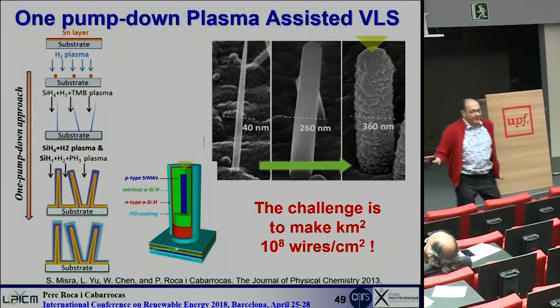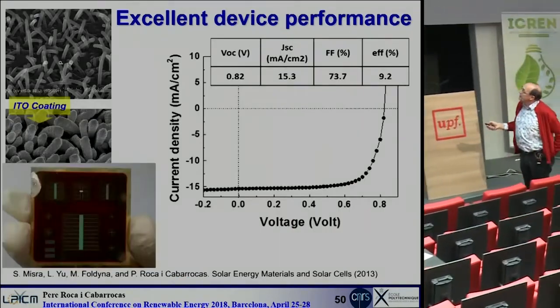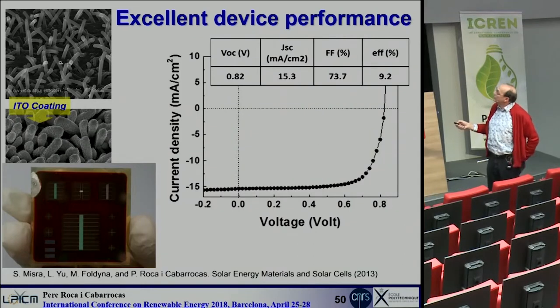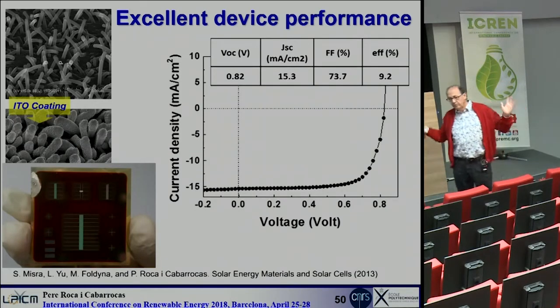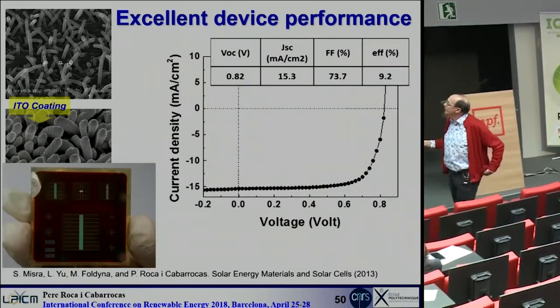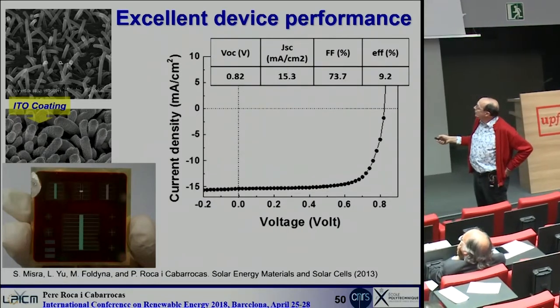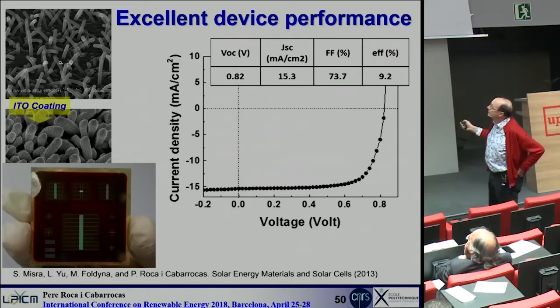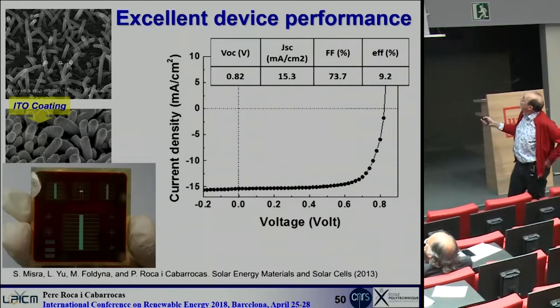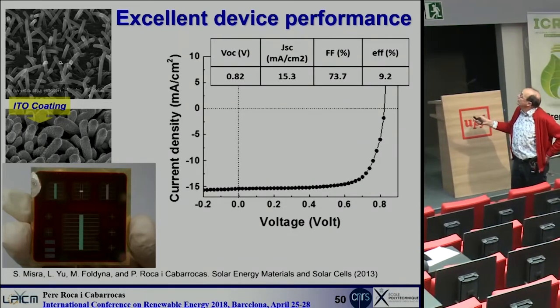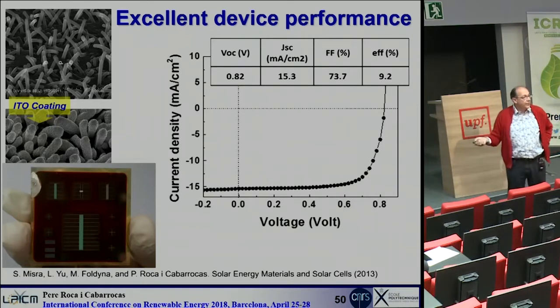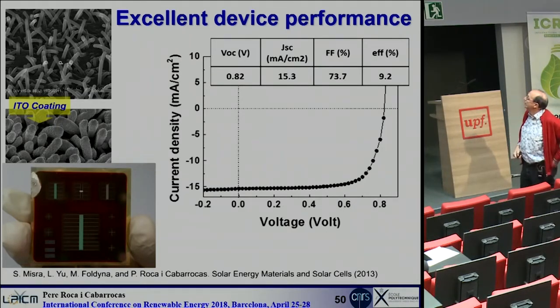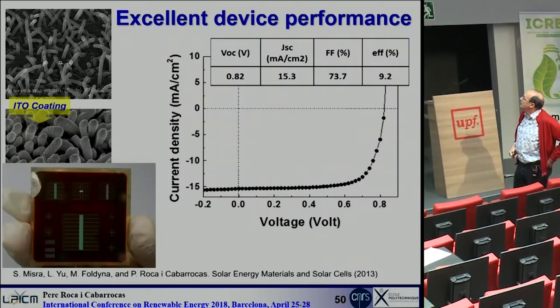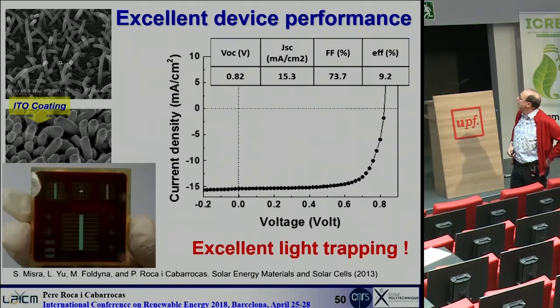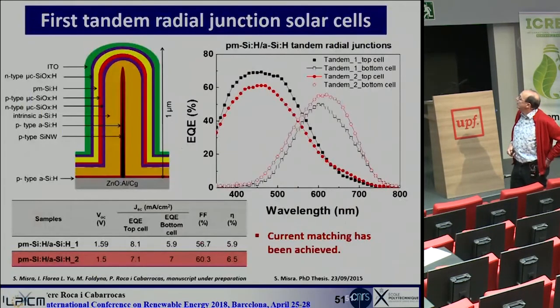Don't trust Murphy, okay? This is our radial junction. So they are awful. Well, no, they are wonderful, but you have wires which go in all directions. They are free to grow as they like. We make the solar cells, we put the pattern, the contacts, and this is the IV characteristics. So I have a very high current. Good collection, VOC, efficiency. So I can make a radial junction which is working better than a single PIN, planar solar cell. We have the excellent light trapping.